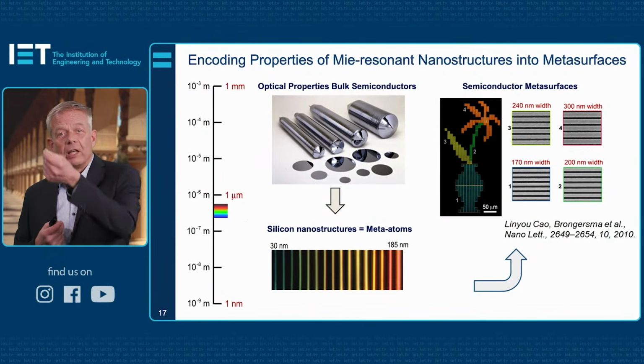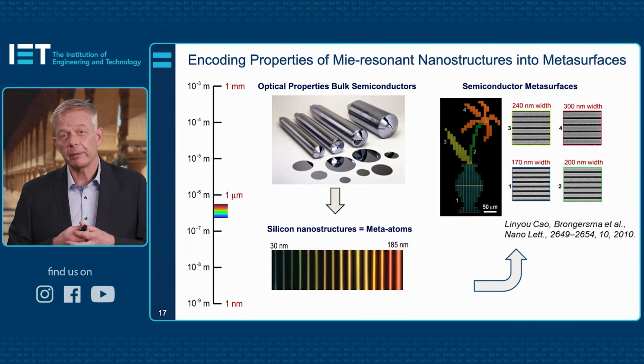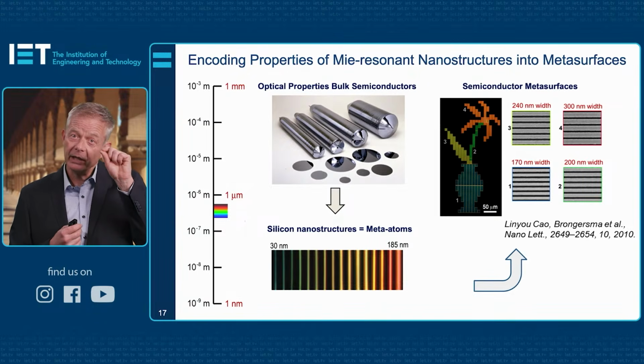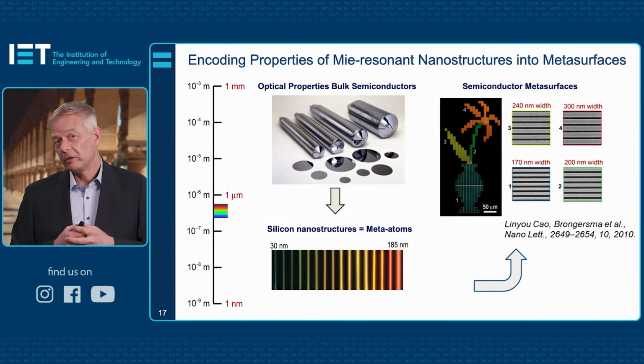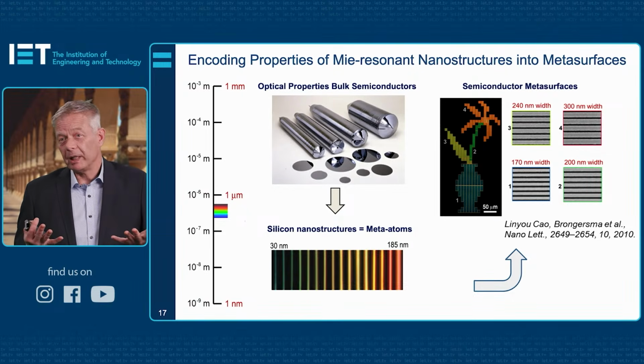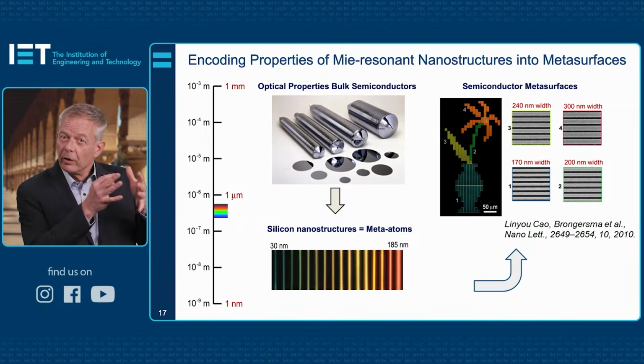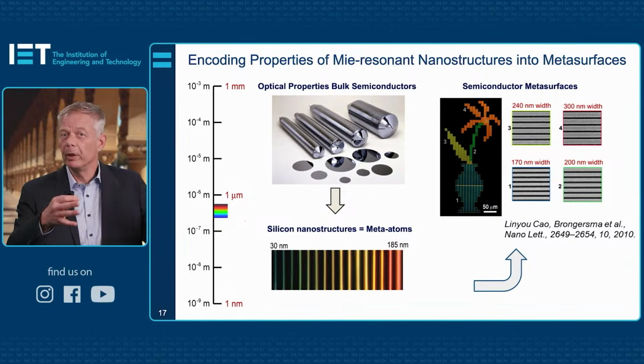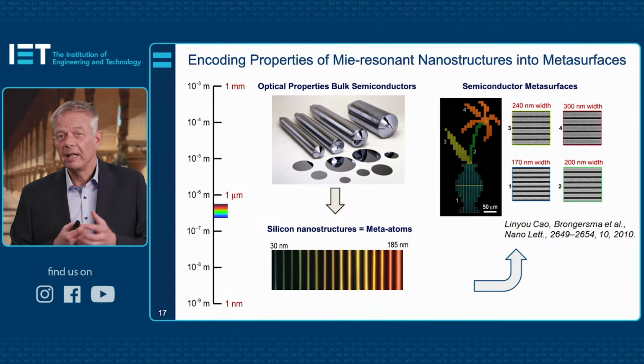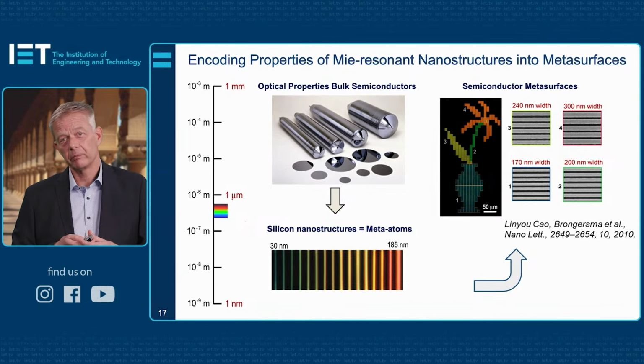Now these are, again, building blocks from which we can make more complex systems. These nanowires we can assemble together in, for example, a beautiful little flower, where the red, green, yellow, and blue colors come from white light scattering from nanowires, but each different nanowire diameter gives you a different light scattering color. So we can start building libraries where, if we understand the light scattering from the different structures by themselves, we can build bigger constructs, metasurfaces, out of the building blocks, meta-atoms, and achieve interesting optical functions over large areas.